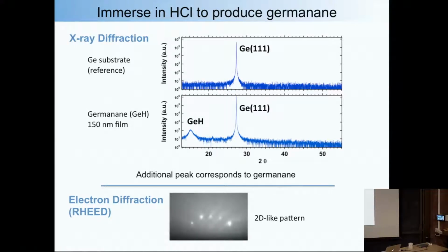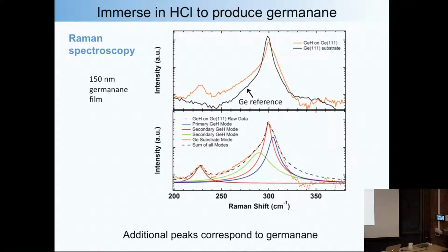So we're very happy. We take this sample after it's been dunked in hydrochloric acid and put it back into the MBE chamber, do the electron diffraction, and we actually see a 2D-like pattern. I won't explain what that means, but it's a 2D-like pattern, so it's still really flat after all that chemical processing.